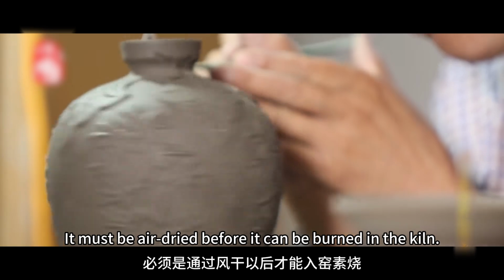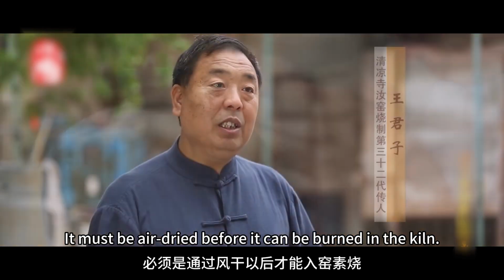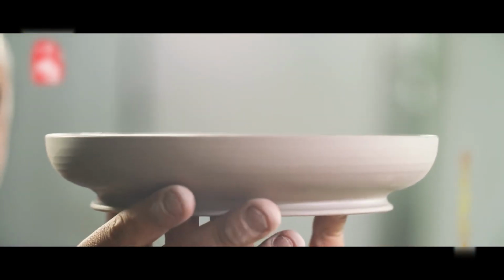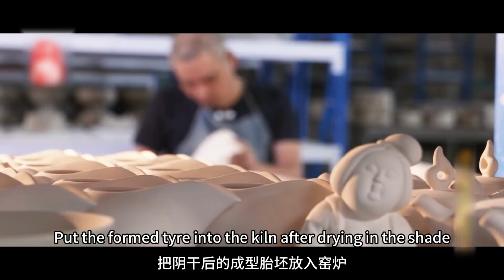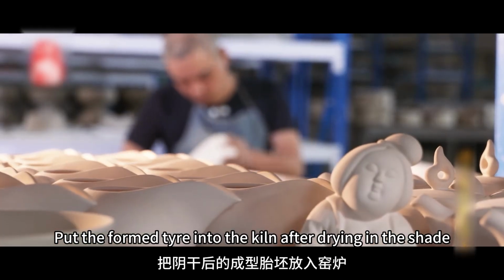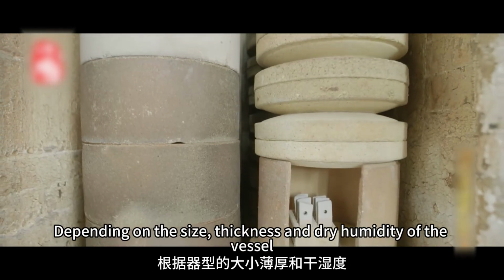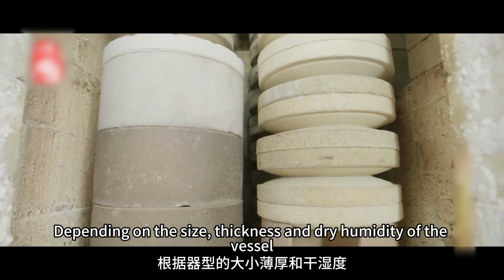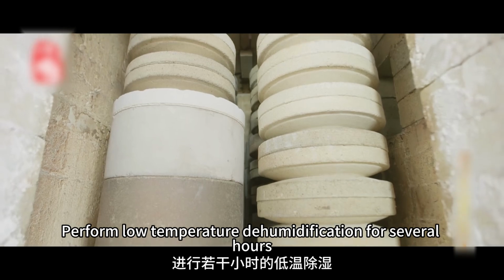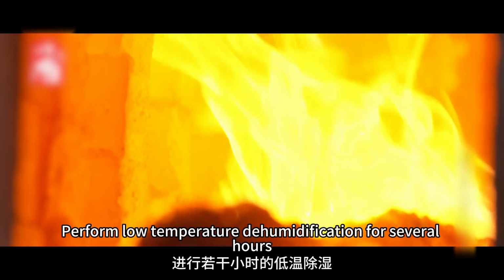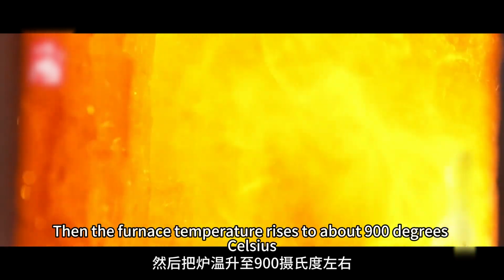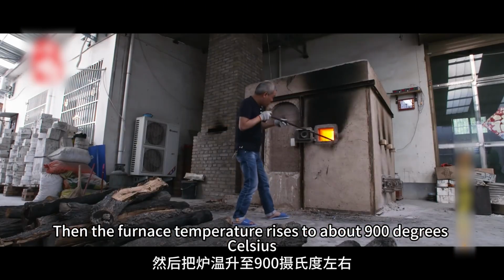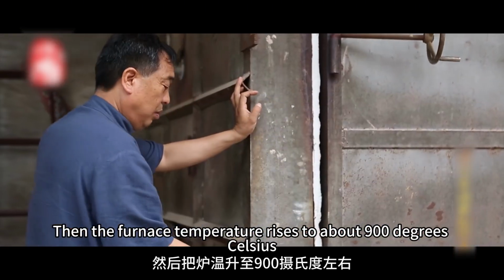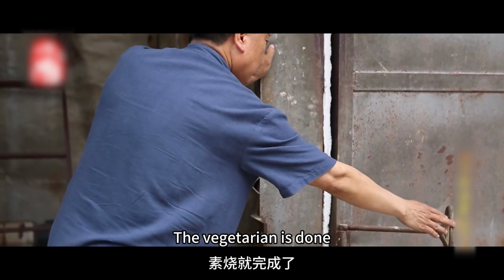Molded tire. It must be air-dried before it can be burned in the kiln. Put the tires into the kiln after drying in the shade. Depending on the size, thickness, and dry humidity of the vessel, perform low temperature dehumidification for several hours. Then the furnace temperature rises to about 900 degrees Celsius. The bisque firing is done.